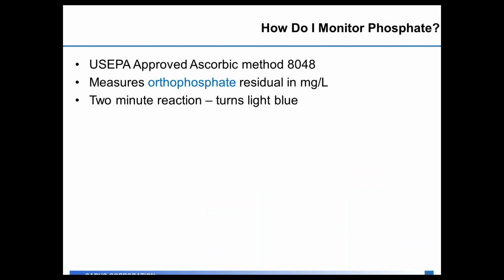Once you start feeding the phosphate, you can monitor how the phosphate is working in your system by measuring the orthophosphate levels in your distribution system. The US EPA has an approved method that you can use, and it measures orthophosphate residual in milligrams per liter. So while you're collecting those samples for chlorine in your system, you can split the sample and use a portion of it for the orthophosphate test.